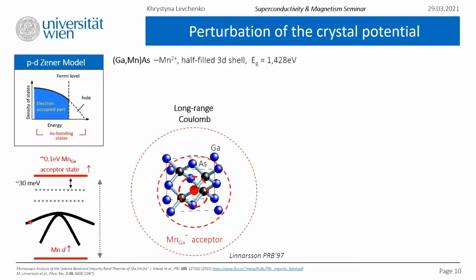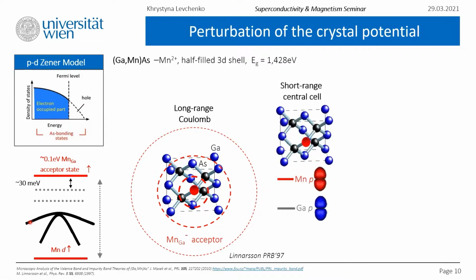A second contribution comes from the short-range central cell. It is specific to a given impurity, and it reflects the difference in electronegativity between the impurity and the host atom. Let us take zinc, for example. It's a non-magnetic acceptor and the nearest neighbor of gallium in the periodic table. When we add it to gallium arsenide by substituting gallium, it would increase the binding energy by 5 milli-electron volts. For manganese, which is the 6th nearest neighbor of gallium, the central cell contribution is again 30 milli-electron volts. The origin of this is in the p-level shift.